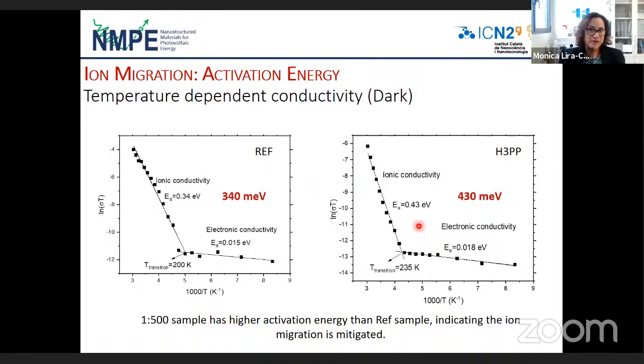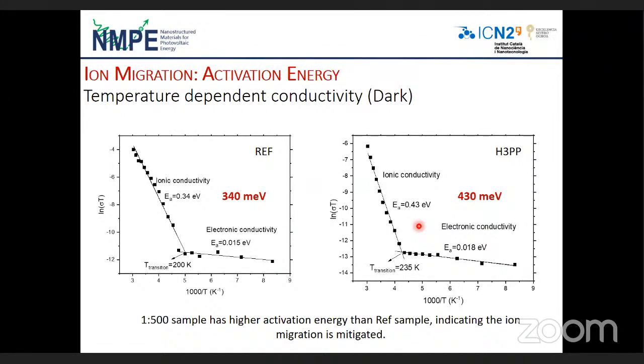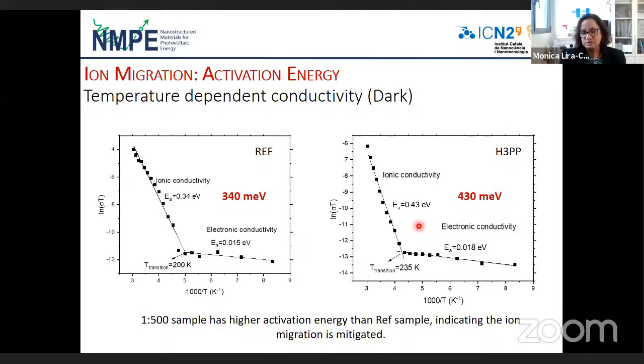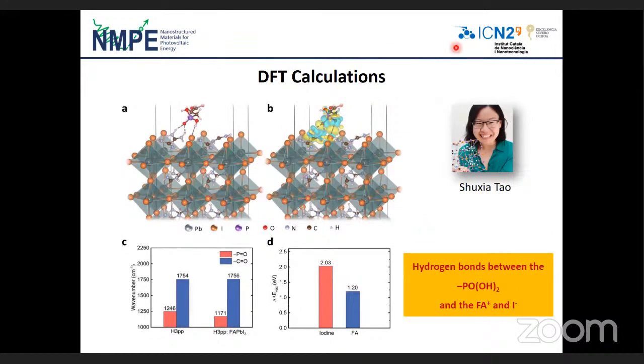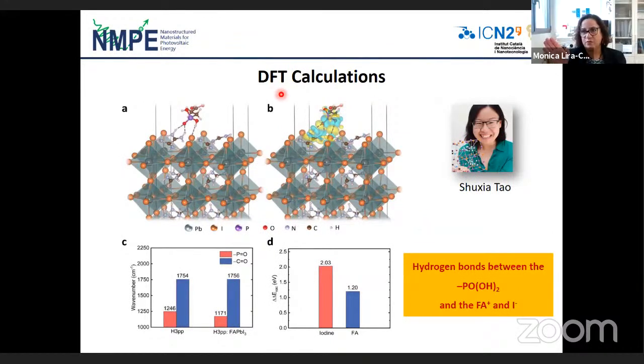So then we were not sure what's really happening, because all of this is not direct evidence. So we also made DFT calculations, and together with the FTIR result, remember the shift on the phosphonate group, it was very well correlated with our DFT calculations. What DFT calculations told us is that the chemical interaction between the halide perovskite and our additive was through hydrogen bonds, hydrogen bonds that come from the phosphonate, the formamidinium, and also the iodine.